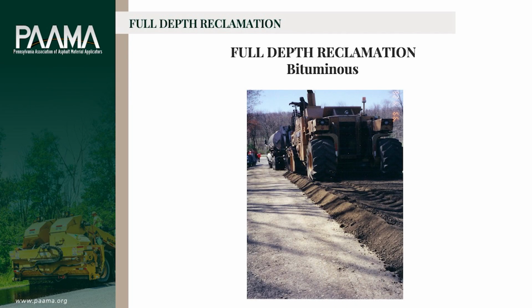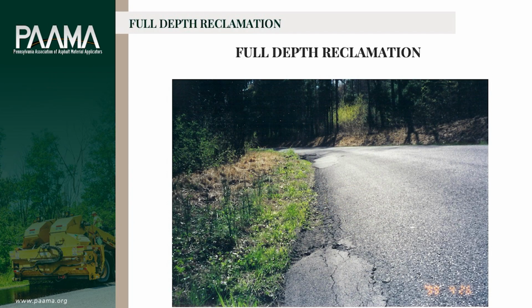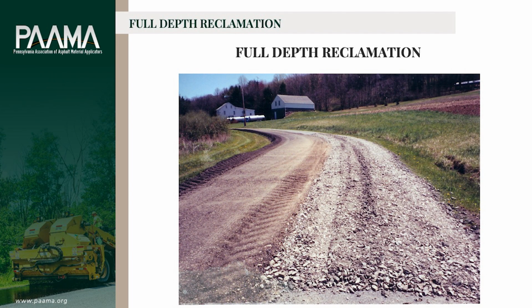Bituminous, so in this picture here, we've already pulverized the roadway, we're now going through, and you'll see that there's a distributor hooked to the reclaimer, and that distributor is putting in the quantity of bituminous material that the mix design called for and mixing it in. Now, one of these roadways had such bad shoulder areas, and you can see here how that cross-section is leaning from the crown out to the shoulder. They wanted to add extra aggregates. So here we see the aggregates on the right. On the left is the first pass of the reclaimer, mixing those aggregates in with the natural soils and the natural road materials that were there, and striking them off.